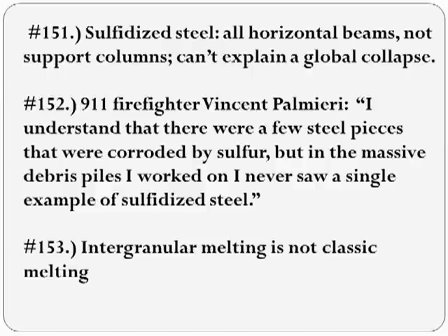If these pieces of sulfidized steel were created with thermates, then we would also have seen a lot of aluminum oxide, which we don't see. Those who assert that the white smoke visible in the fires was the aluminum boiling off may not realize that the boiling point of aluminum oxide is 5,390 degrees Fahrenheit, 1,000 degrees above the hottest temperature of any thermate. Not only is there no aluminum oxide and no way to account for its absence, there is no sulfur in the Harrit-Jones paper. It's not there, and therefore no thermate.